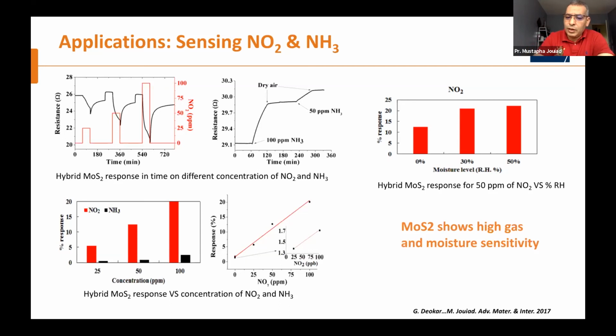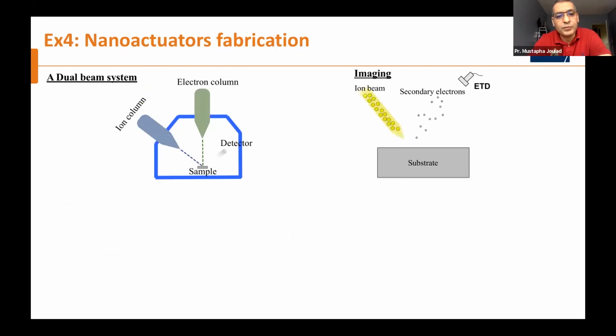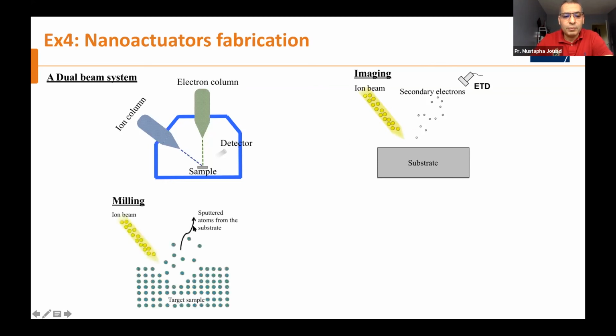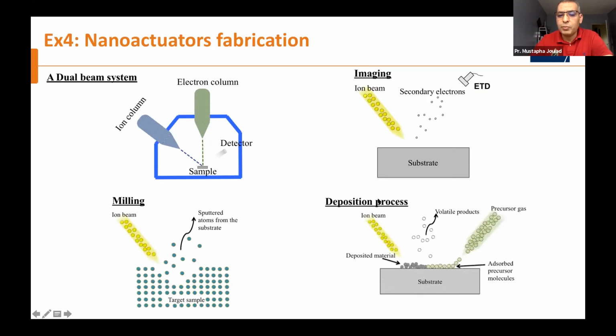So basically, our MoS2 shows high gas and moisture sensitivity, and is very competitive with monolayer MoS2. So the fourth example concerns nano actuator fabrication. To do that, we used a dual beam system consisting of an electron column and an ion column, known under the name focused ion beam, FIB-SEM. This system can do imaging, milling, and also deposition. So we use these three properties of the focused ion beam to fabricate actuators.